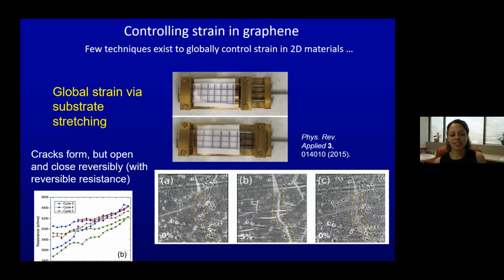And we measured resistance in this case. You can see that the resistance was reversible. It went up when it was cracked, and then it went back down again when you released the strain. So it's almost like the cracks would close up again in graphene, which is something really useful if you're trying to make flexible graphene devices and you worry about it cracking. You know that when you release the strain, it basically goes back to the way it was. So this was something interesting, but it was really making lemonade out of lemons, because we didn't really want cracks.